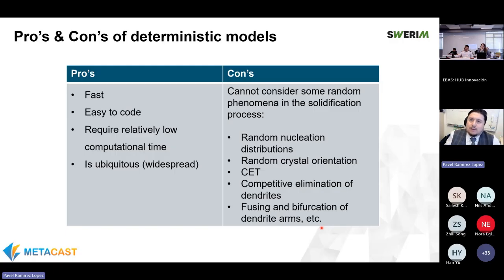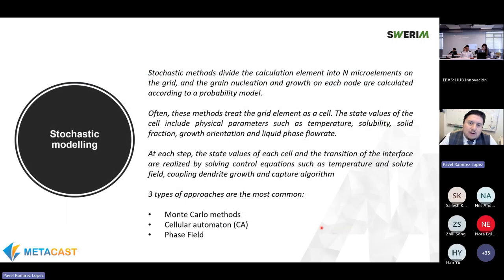Because we have the heat transfer profile, we can calculate the average grain size distribution. However, we don't have these effects of competitive elimination of dendrites. And the same goes for fusing and bifurcation of dendrite arms, and breaking off arms to form new nucleation sites. All these effects are lost. And that's the reason why we approach the stochastic models.